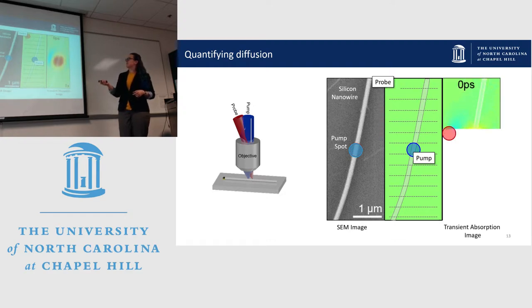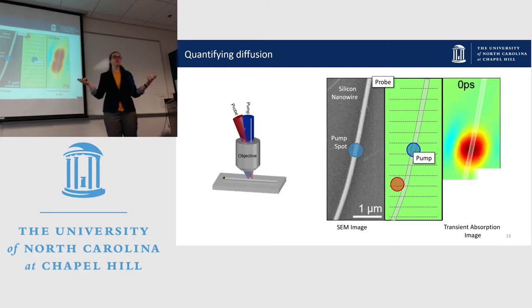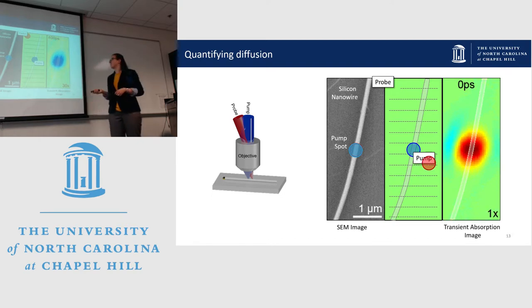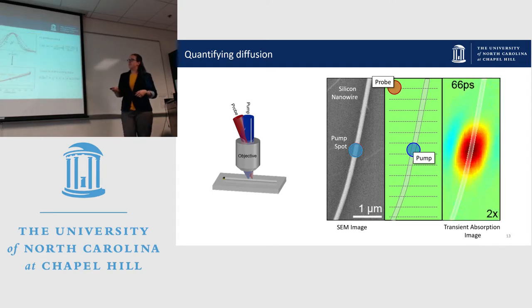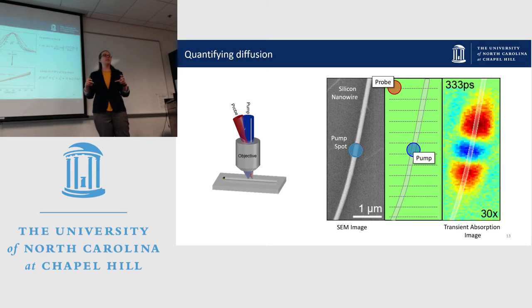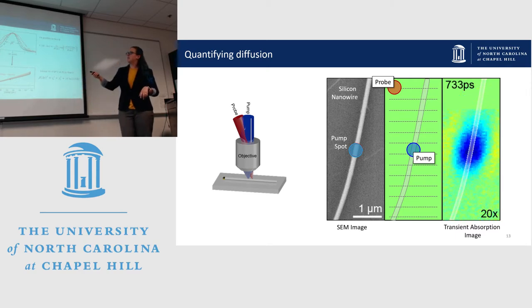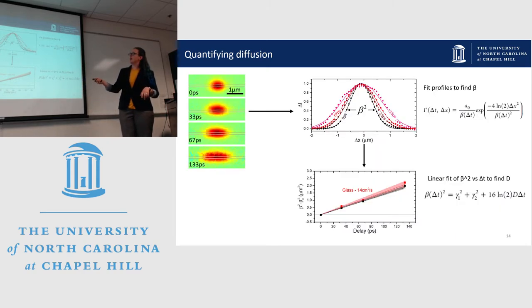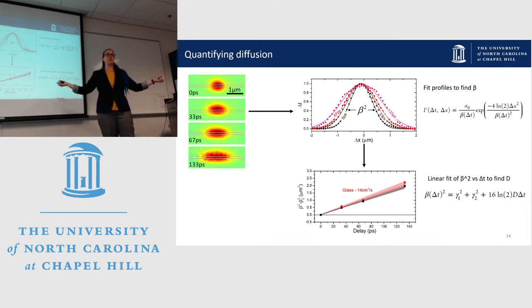We do this for several time points. We create a movie of carriers traveling along the wire. We can then fit those. We can take the stills from that movie, add up the signal in each of the columns, plot that intensity versus the x position, and we get these nice Gaussian-shaped curves, which we can then fit. The diffusion coefficient then comes from how quickly the full width half max of those curves changes with time.